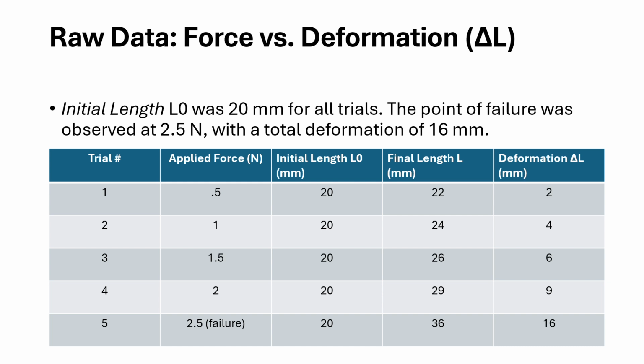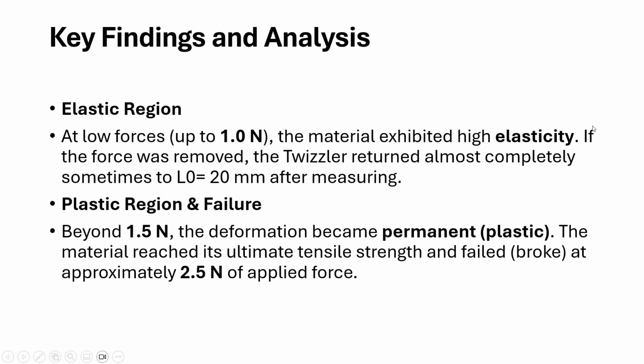For trial 2, I applied another half, making it 1 newton, and it changed 4 millimeters. And then for trial 3, again, I added a half, and it deformed 6 millimeters. And then in trial 4, with 2 newtons, it stretched to 9 millimeters. And then in trial 5, it eventually failed, where it deformed 16 total millimeters.